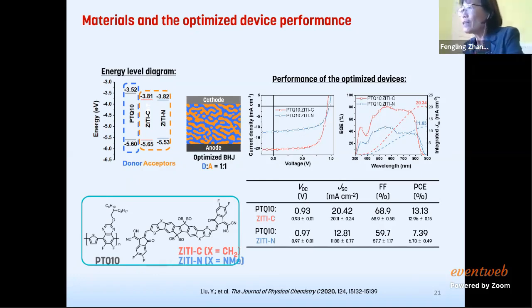For the small energy offset, we get an efficiency of 13, which is already quite decent. The voltage you see is close to 1 volt, which is quite big with a narrow band gap. For PTQ10 with ZITI-N, with the negative HOMO levels, you can see the efficiency drops to half compared with the ZITI-C. But even then, we still think it's quite impressive, because the energy offset is negative. You should remember it's negative. It's supposed to not work at all, but we still get 7% power conversion efficiency. It's really amazing. Also, the fill factor close to 60 is quite good, and the current of 12 or 13 milliampere per square centimeter is also a very nice number, considering the energy offset is so small.